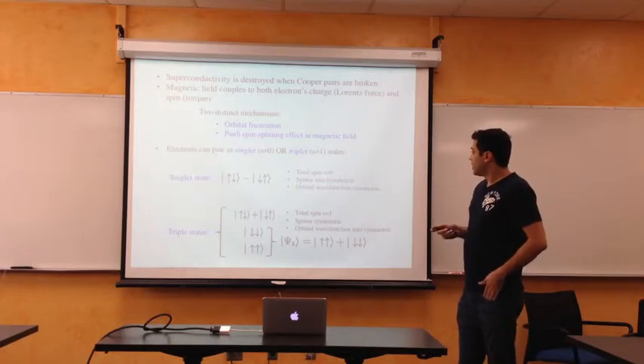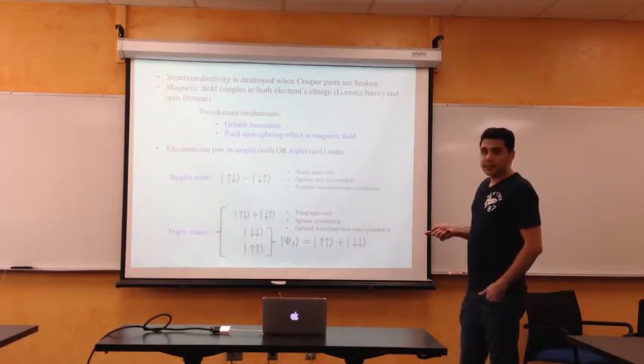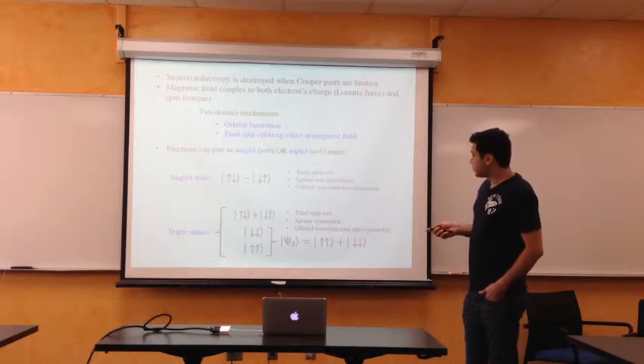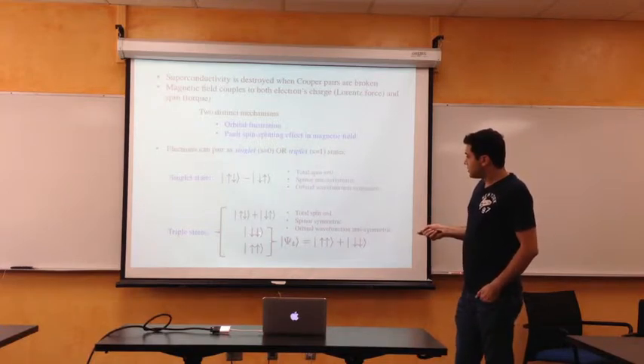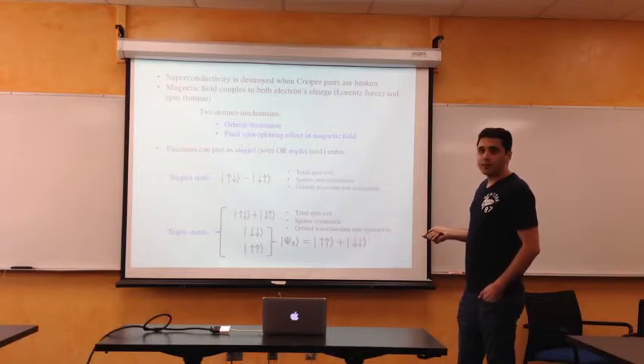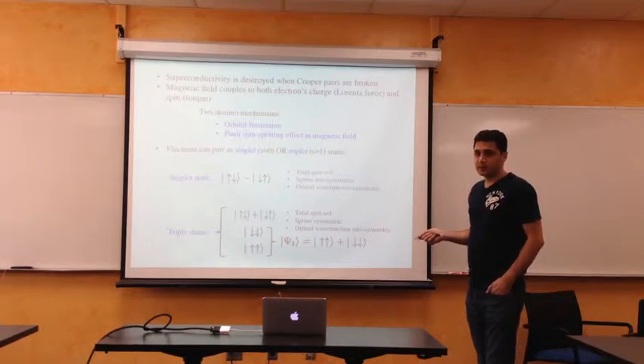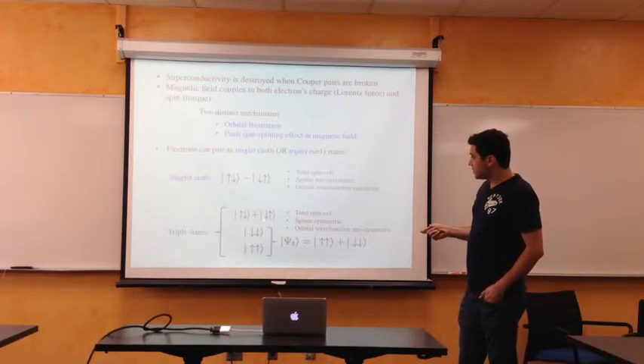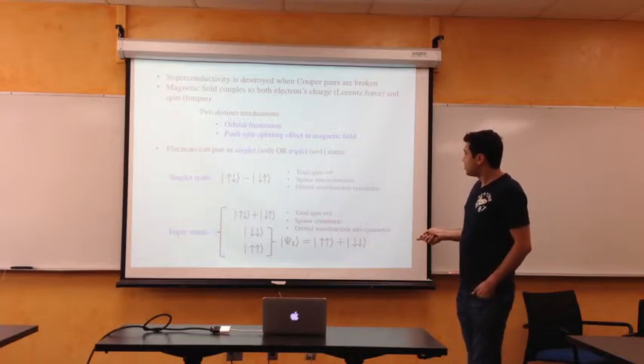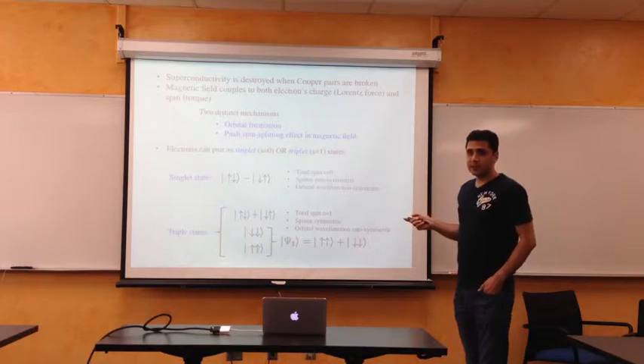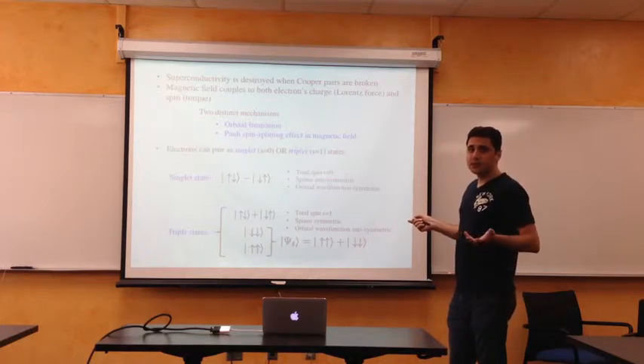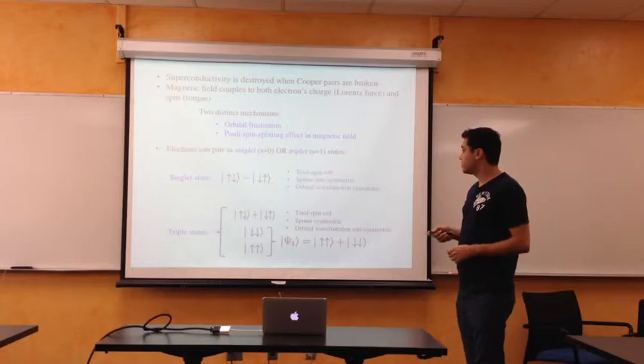In the triplet state, we have three possible choices, and one of them is a linear combination of down-down and up-up, which is not sensitive to Pauli spin-splitting effects. So although there is a state that is sensitive, with spins anti-aligned, if we choose a linear combination of up-up plus down-down, we are in the S1 triplet state, and the Zeeman effect is moot—it doesn't play a role anymore.